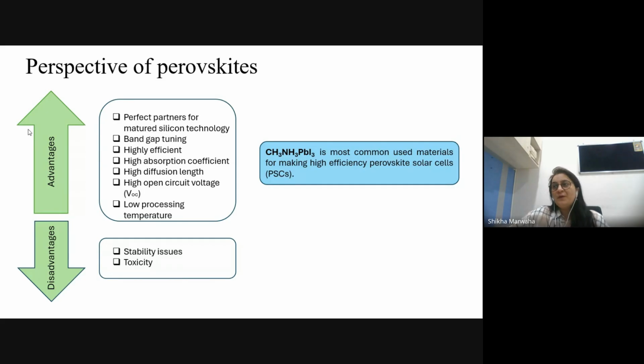This is very important because in silicon, if anybody has worked on carrier selective contact architecture or heterojunction with intrinsic thin layer structures, HITs for silicon, we see that there are certain layers in which the temperature should not increase beyond 500 degrees Celsius, because then that layer starts to degrade. So we need a technology on top of silicon that does not hamper its properties, but just adds value to it. Perovskite can be manufactured at a processing temperature of near about 200 degrees Celsius, so it should work. So yes, this is one of its advantages.